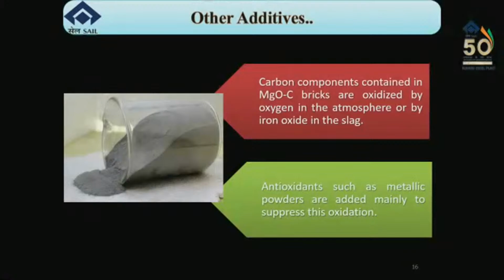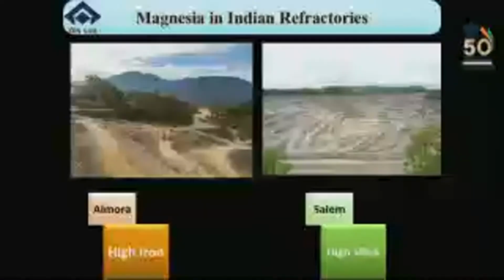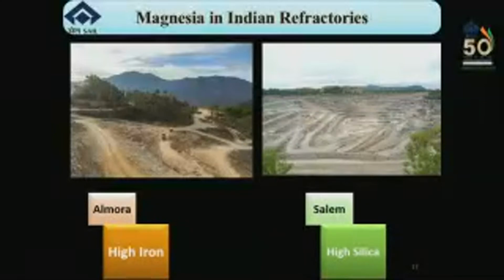There are some other additives that are also added during the manufacture of magnesia carbon bricks. Carbon components contained in magnesia carbon bricks are oxidized by the oxygen in the atmosphere or by the iron oxide in the slag. Antioxidants such as metallic powders are added mainly to suppress this oxidation.